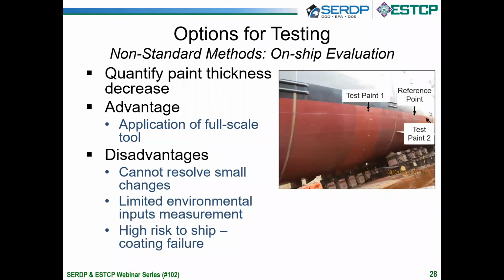Something that we have tried and we have a decent amount of experience with for the legacy copper ablative paints that we've been using for a few decades now is we can evaluate the thickness change before cleaning and after cleaning directly on a ship hull. The advantage here is that we're applying the full-scale tool to in-service coating, but the disadvantage to this technique is that it's very difficult to resolve small changes in paint thickness, and we have a very limited ability to assess the environmental input from the coating in terms of the particulate and the biocides.